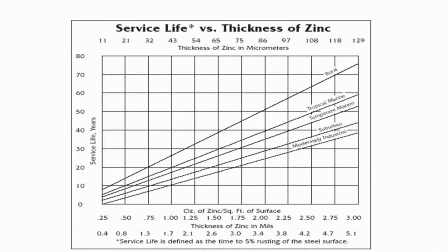Those particles get deposited onto the surface, and when they are deposited, naturally the absorptivity of the surface increases. So, the surface will be more prone to absorb moisture from the environment than in the typical rural environment, where there are not many impurities. As a result, in an industrial environment the service life of the component against corrosion is much lower than in a rural environment.